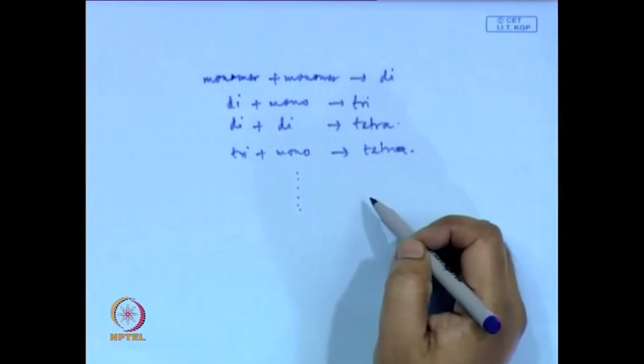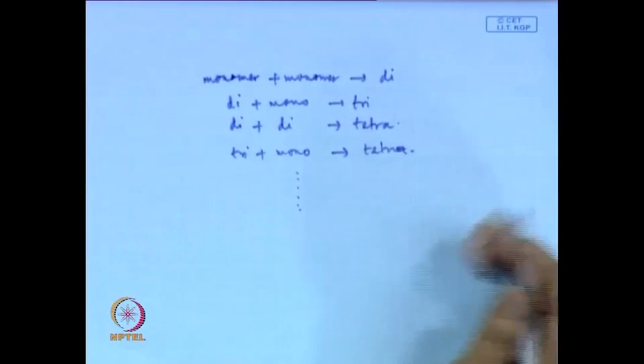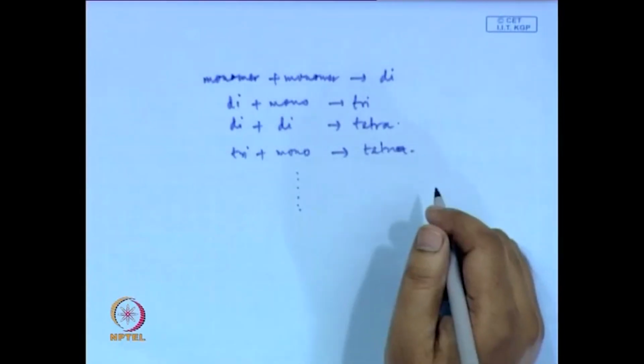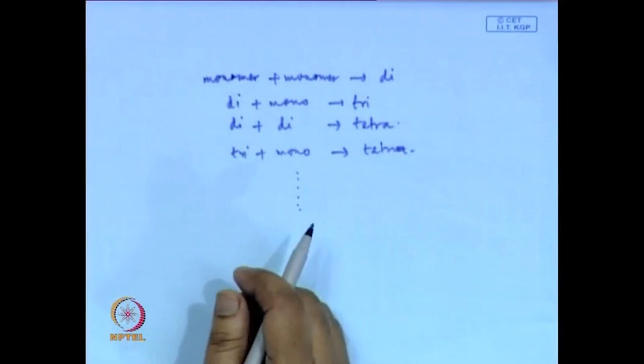If you stop a step growth reaction after some time, before completion, what will you get in the polymerization medium? If you recollect, in chain polymerization, if you stop the reaction in between, after a small amount of monomer has reacted, you will find high molecular weight polymer as well as lots of monomers and also initiator molecules.